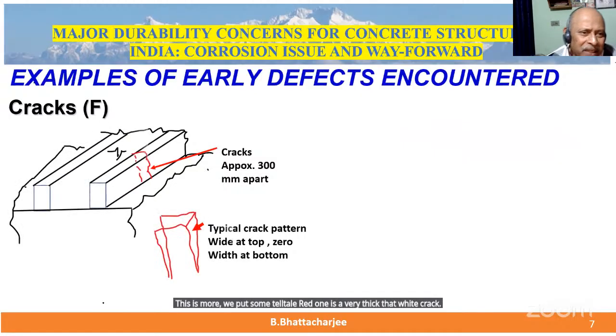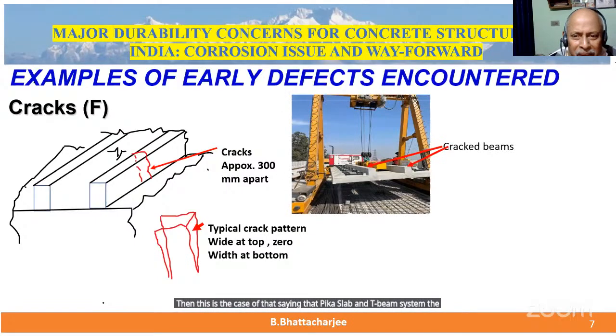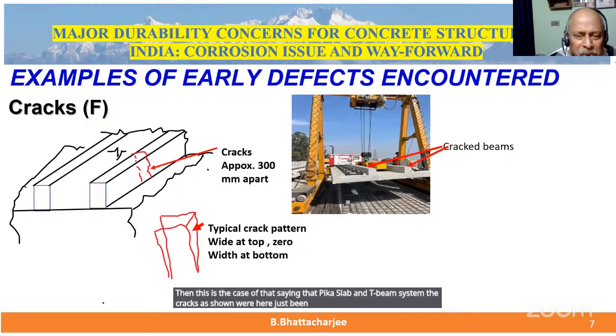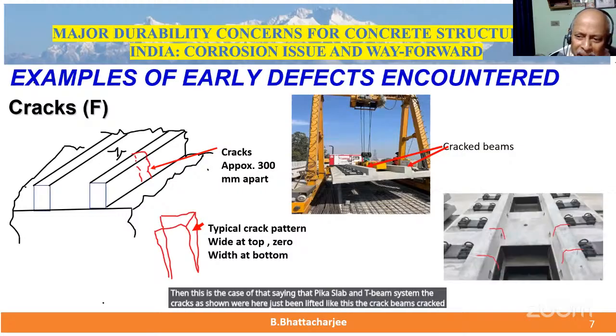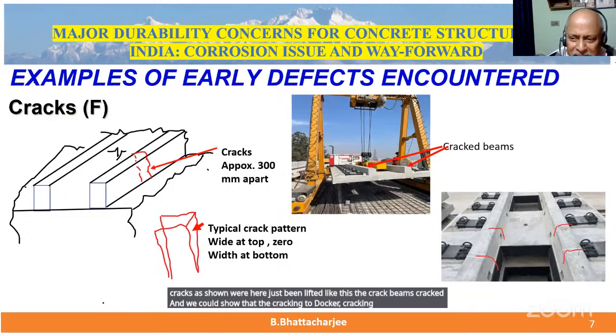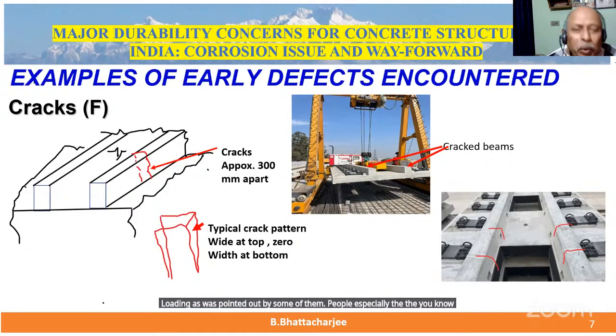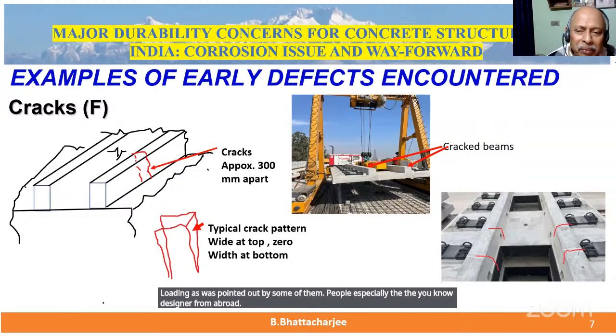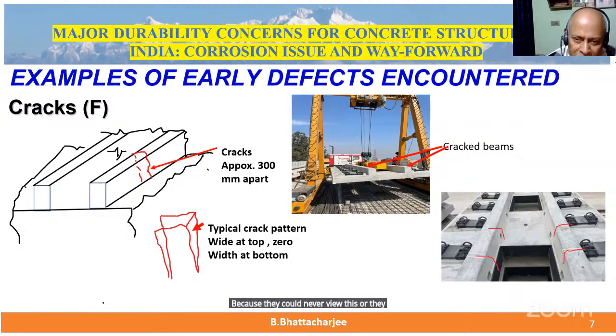Then this is the case that I was saying, the precast slab and beam, T-beam system. The cracks as shown were here. This has been lifted like this. The beams were cracked, and we could show that the cracking could occur at certain spacings, and not because of structural loading, as was pointed out by some of the people, especially the designer from abroad, because they could never view this, or they actually suggested the handling method and all. But the Indian environmental condition is not the same as even the Mediterranean.